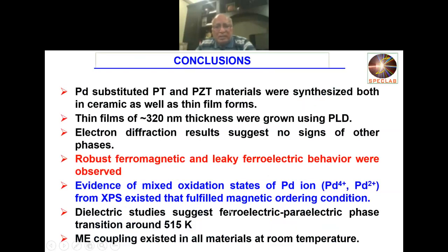Well, I conclude my talk here. Just to say, the Pd substituted PT and PZT materials were synthesized in ceramic as well as thin film forms. Film thickness was something like that. Electron diffraction results suggest no signs of other phases. That is, we did have phase purity. Ferromagnetism was robust, no doubt about it. But leaky ferroelectric behavior was observed.